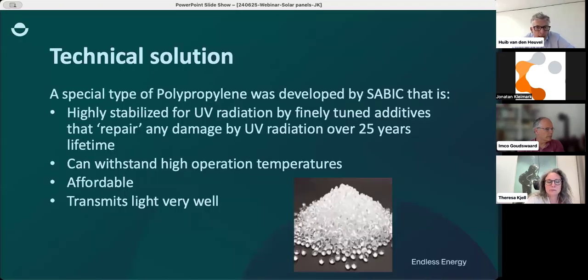Next one. So the solution that we basically decided for is to use a similar polymer as Endurans uses. It's also a polyolefin. This one is specifically a polypropylene polymer, but it's part of the polyolefin family. And the technology that SABIC developed is to stabilize those polymers for long-term outdoor use, with high exposure to UV, thermal load, and humidity, by stabilizing the bulk of this polymer for those loads. So it's not using any additional layers. It's really in the bulk that the material has been stabilized. And it's with a package of different stabilizers that actually can repair the material while it's being attacked by these outside stresses.